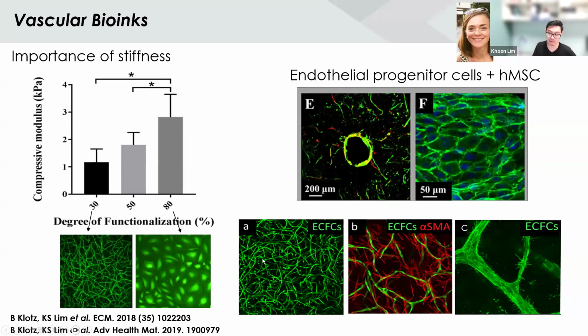What we also then found is that these endothelial cells really need support cells, and that's what they do in the native vascular biology. All of these endothelial cells or microcapillaries have smooth muscle cells that go to stabilize them. So if you co-culture these endothelial progenitor cells along with some mesenchymal stromal cells, you can see the capillaries form, the stromal cells around to stabilize them. And it's also really nice to see that the progenitor cells are sprouting and forming these really nice network protrusions, to try to form more interconnected networks within these vascular bioinks.